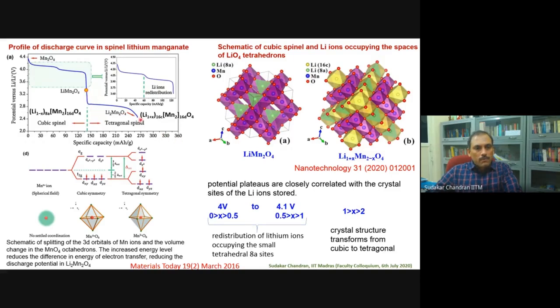In this particular compound, it was shown that you can also insert a second lithium. LiMn2O4 is spinel, you can put one more lithium, and they showed it is possible. Therefore, the capacity could be increased to 270 milliampere hour per gram. Beautiful science came out of this. In fact, the moment you try to put the second lithium, the voltage which was at 4 decreases to close to 2.83. The reason for this is the lithium, which was initially at 8A position, now moves to 16C position. And there is an associated distortion in the structure.